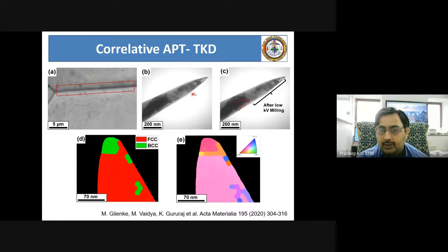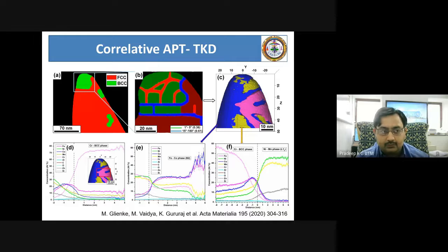Look, this sharp needle in the TEM, and you can see the grain boundary is located here. So you selectively mill away unnecessary region, get this grain boundary at the apex of the tip, and do the diffraction so that you can see the body-centered cubic structure precipitate sits on top of the grain boundary, and the matrix is made of face-centered cubic structure. You can get the orientation information. Take the same to the atom probe, then we will be able to see what is the precipitate phase that is sitting on a grain boundary.